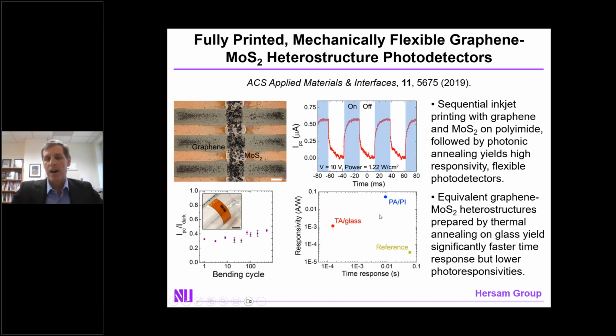Whereas if you do photonic annealing, which is a much faster evolution of the ethyl cellulose, that leads to a more disordered matrix, which gives you a compromised time response, but gives you a much higher responsivity. The bottom line is that the way in which you do the curing also influences the final properties. But what I want to stress is that while these initial results were promising, the responsivities are really quite low.